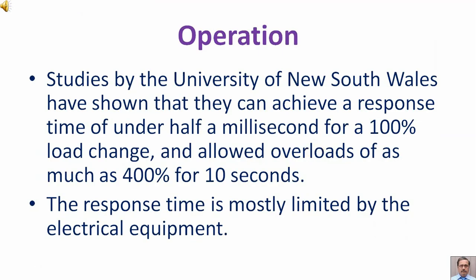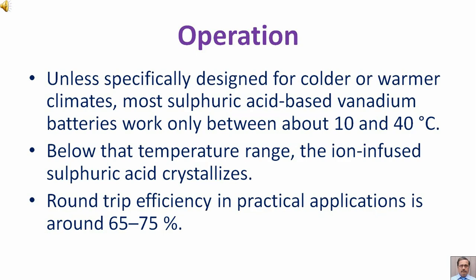Operation. Studies by the University of New South Wales have shown that they can achieve a response time of under half a millisecond for a 100% load change and allowed overloads of as much as 400% for 10 seconds. The response time is mostly limited by the electrical equipment.